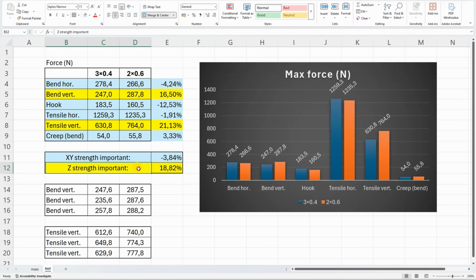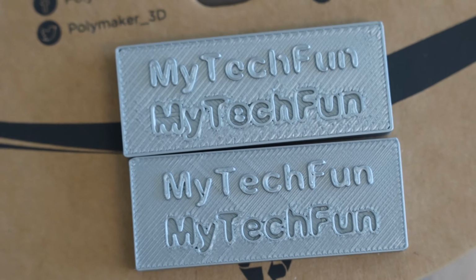So yes, the method will improve the layer adhesion, but the effect along the x and y is unknown, but it looks like in this case the change is not significant. Looks like with this method we can improve the layer adhesion by approximately 20%. But if you need strength along the x and y, then the improvement is not so obvious. Sometimes the part will be even a little bit weaker, but knowing that the printed part is anisotropic, this means the strength along the x and y is much bigger compared to the z strength, I don't really mind. And if on a mechanical part I don't have some small details, then I will use this method.